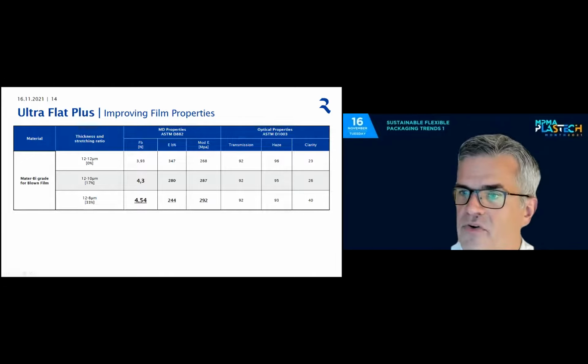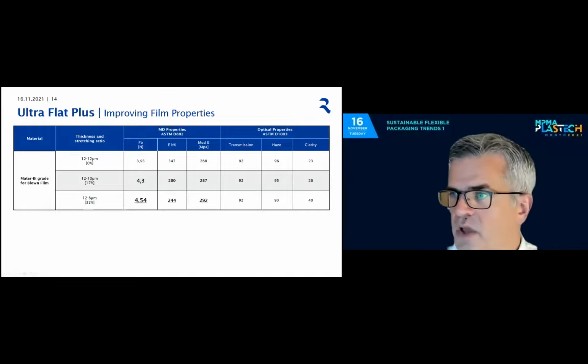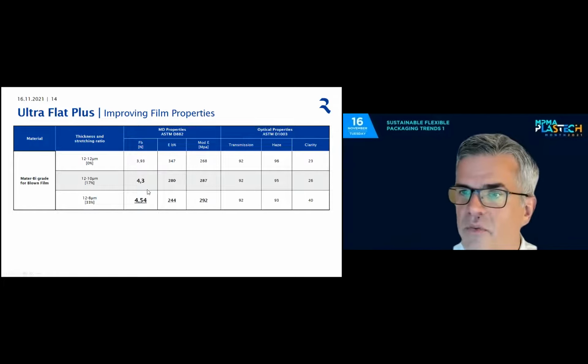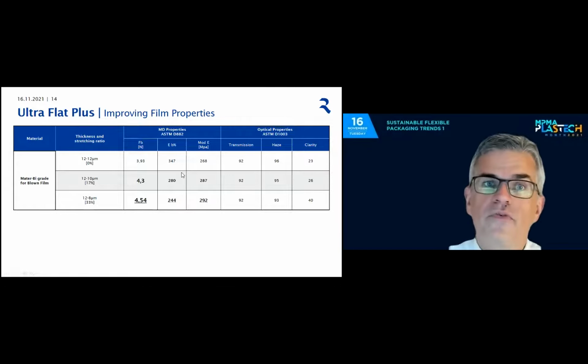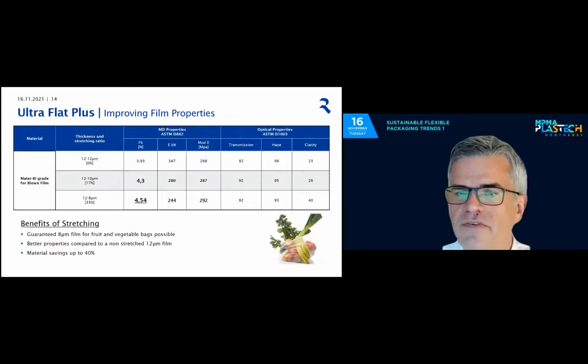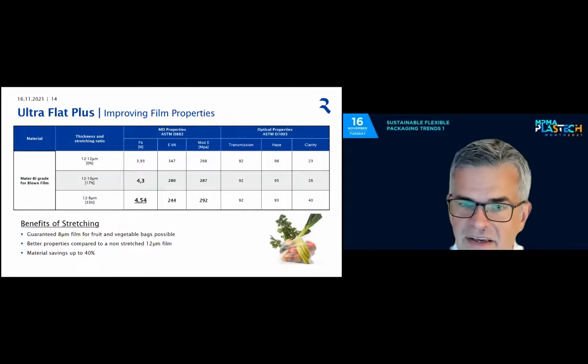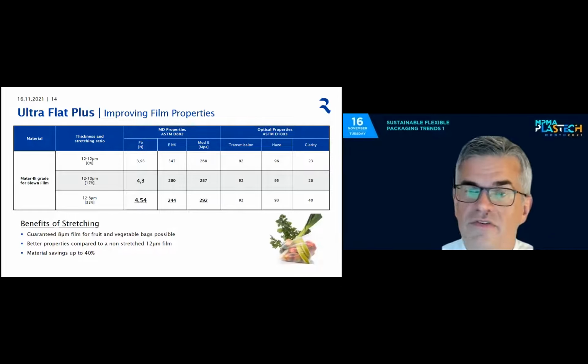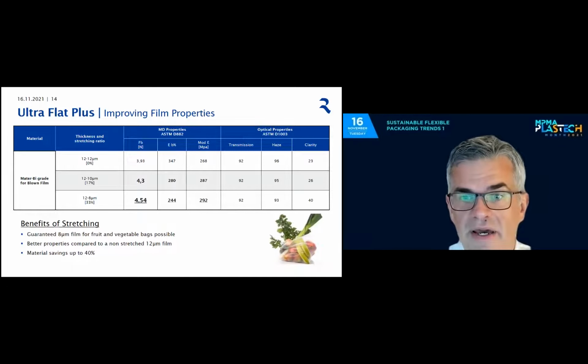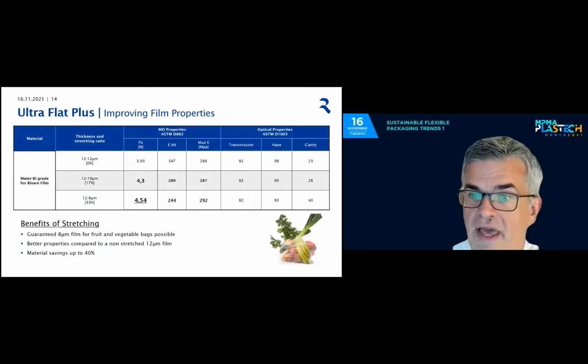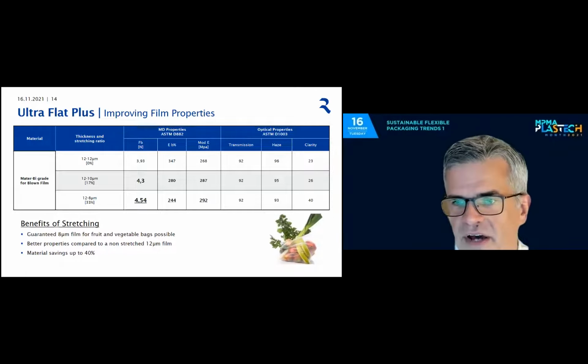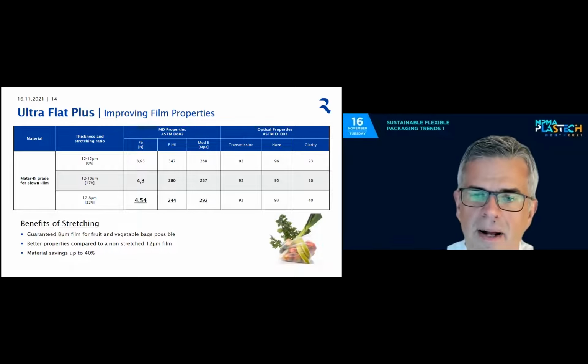And what we see is that we improve the stiffness of the film, we improve the clarity of the film, and we improve the force and reduce the elongation at break. So we improve those disadvantageous properties of biopolymers by using machine technology. So exciting, we can reduce the thickness, which is usually 12 microns. We down gauge it to 8 microns. We have better properties of the 8 micron film compared to the non-stretched 12 micron film. The exciting thing is down gauging and getting better mechanical properties. About 40% is the saving of materials.